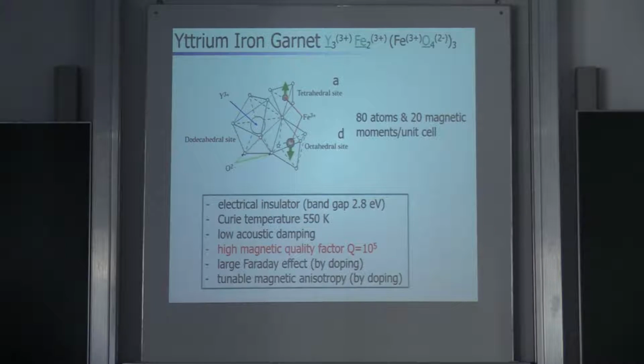So yttrium iron garnet does not occur in nature. It's an artificial compound, and its magic is the very high quality with which it can be grown, either as single crystals, but more recently also in thin films. Now the reason for that is simply that people have worked on this for several decades. Material science is a slow science. It takes a long time before you find out how to grow material in sufficient quality, and that's the nice thing about YIG. So we know that it's close to perfect, and then it's a good material to really understand the physics. So I would also like to say that YIG is the two-dimensional, high-mobility two-dimensional electron gas for magnetism.